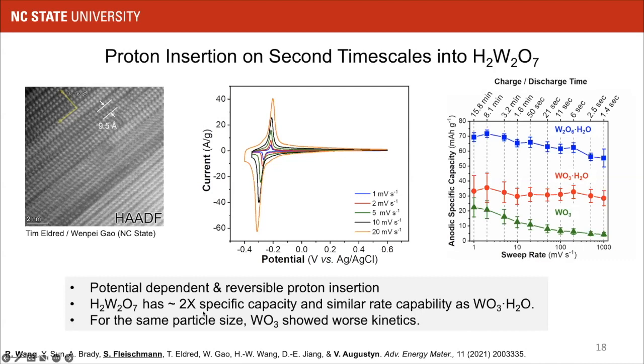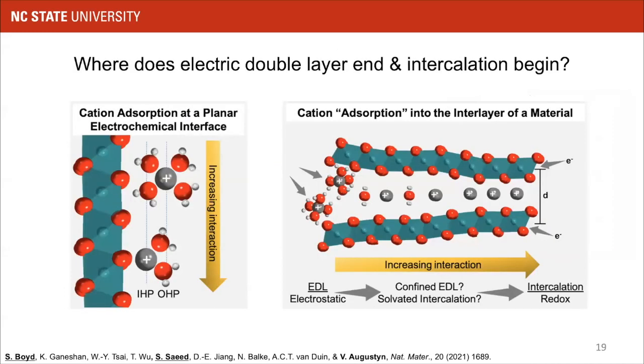And we did achieve our goal of having about two times the specific capacity of the tungsten oxide monohydrate while maintaining very good rate capability. So that's the comparison with the blue, this material, the H2W2O7, and then the monohydrate down here. And then for the same particle size, we still see that the anhydrous material shows worse kinetics. So we were able to use metastable transition metal oxides to improve the performance.